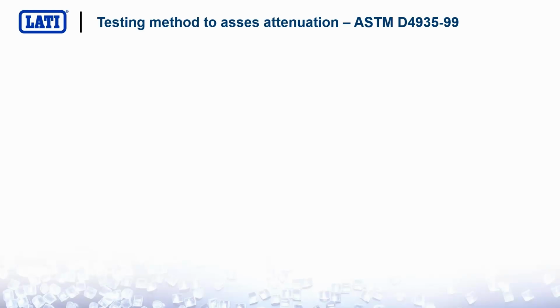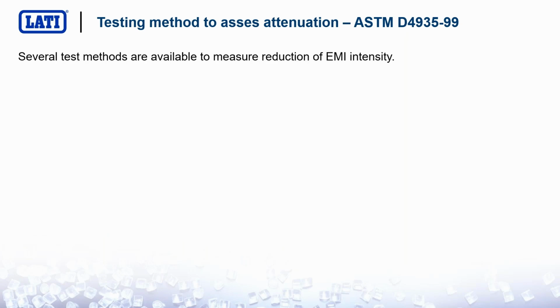The testing method that we used was selected with the University of Aachen. Please note that there are plenty of methods to measure EMI shielding, but not all these methods are equivalent, and some of them are not suitable for some applications or some materials. The test that we used is the ASTM D4935-99, which is called the coaxial transmission line test method.